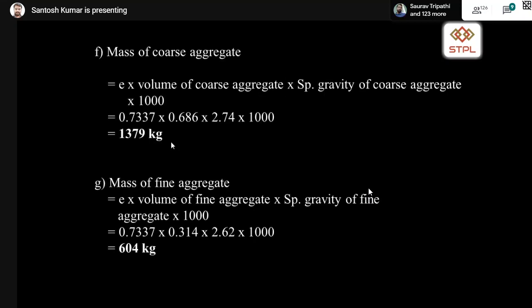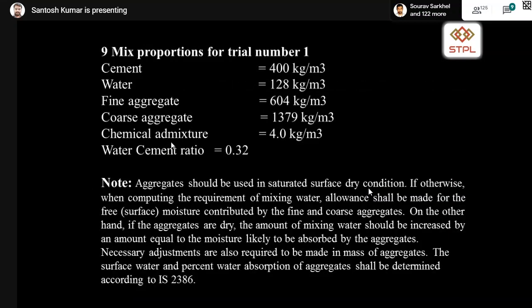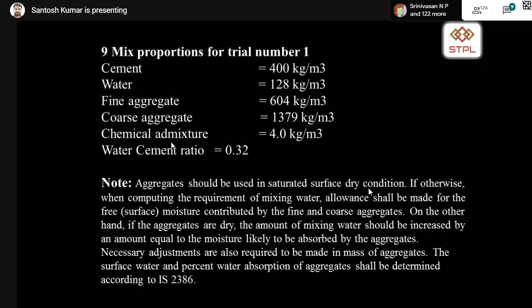So 0.7337 is multiplied by the volume of coarse aggregate 0.686, multiplied by the specific gravity of coarse aggregate, multiplied by 1000. The mass of coarse aggregate is 1379 kg, and in the same fashion the mass of fine aggregate is 604 kg. Your mix design is done. The water cement ratio is 0.32 and the cement content is 400 kg per cubic meter.